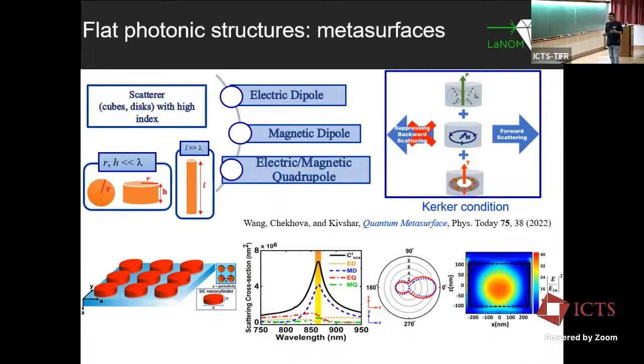You take dielectric spheres of submicron diameter, or scatterers of different shapes, and arrange them in a certain symmetry. You excite them, and they excite electric dipole, magnetic dipole, and other higher order poles. Then you can interfere them in such a way that you get complete forward scattering with near zero backward scattering. In the literature these are called Kerker conditions. At these conditions, you can localize light inside the material, even though there is no spatial cavity.